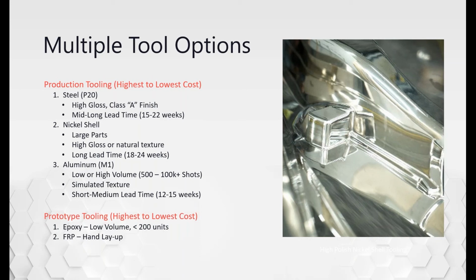And aluminum, M1 aluminum tends to be kind of our go-to for almost every program that we work with. You can get very good polish to get the Class A finishes and glosses that we're looking for. And with any of these, but especially with aluminum, doing simulated textures, you know, leather grain, wood grain, basic bead blasting or steel shot, something like that, can readily be done in aluminum. It can be done in P20 steel as well, and you can do it in nickel shell, but changes to nickel shell tend to be much more difficult to accomplish.